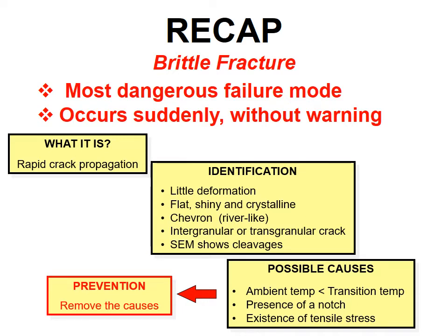Now that we have come to the end on brittle failure, let's do a quick recap. Firstly, we must understand that brittle failure is associated with rapid crack propagation. Brittle fractures can usually be distinguished from ductile fractures by an almost complete absence of plastic deformation. Fracture occurs at stresses below the yield stress and are often flat and shiny. It is possible to trace the fracture path to its origin by interpreting the chevron markings on the fracture surfaces. With a brittle fracture, the fracture origin is often a notch or a small crack, usually on the surface. When examined microscopically, brittle fracture may be transgranular or intergranular, and scanning electron microscopy images reveal cleavages.